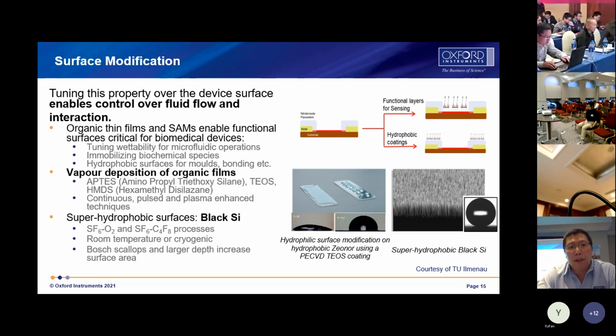Organic thin film can be deposited by vapor deposition. Black silicon is another surface which has been attracting lots of interest in the recent past. Black silicon is a composite of nano-structured silicon, which looks like nano needles or nano spikes. Black silicon can be made by a plasma etching process based on SF6/O2 or SF6/C4F8, even the Bosch process. Different methods make different topographies. You can see that a water drop on a black silicon surface keeps a purely round shape because the surface is super hydrophobic.